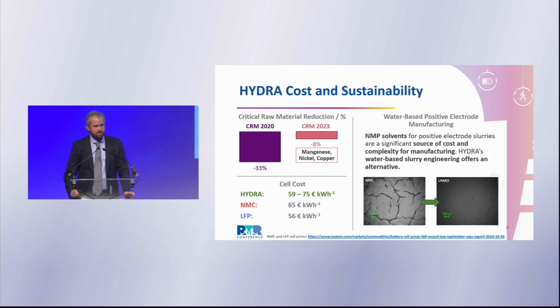And we can see that by doing this, we've managed to reduce the critical raw material content in the battery by 33% compared to the 2020 CRM list and by 8% compared to the 2023 CRM list. And the reason for the difference is the addition of manganese, nickel, and copper on the critical raw materials list in 2023.